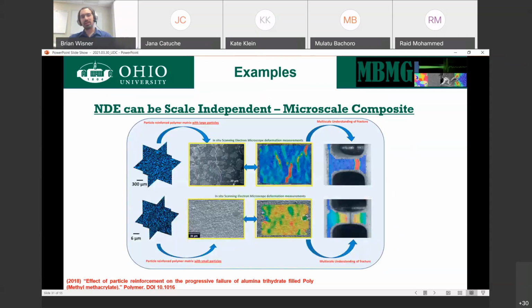Once we do that, we can then bridge the microstructure, full three-dimensional microstructure, to how the material fails based on the non-destructive testing. This is just with DIC, not even considering acoustic emission yet. And it's very clear that in the case of the first material, we have large particles and it's very brittle. In the case of the second material, we have small particles. Both of these materials are made from the same things. The only difference is the size of the particle. And we have much more ductile failure.